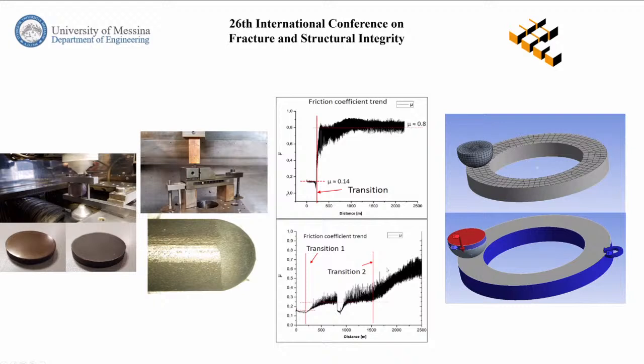In particular, we made two tests that I called in the presentation test A and test B. This is very important because one of the inputs of the finite element model that we build later is obviously the friction coefficient. So we need to know exactly the value of the friction coefficient, and after that a finite element model is built, as you see here on the right, of the pin-on-disc apparatus, in which obviously we consider the load condition and the rotational speed condition.